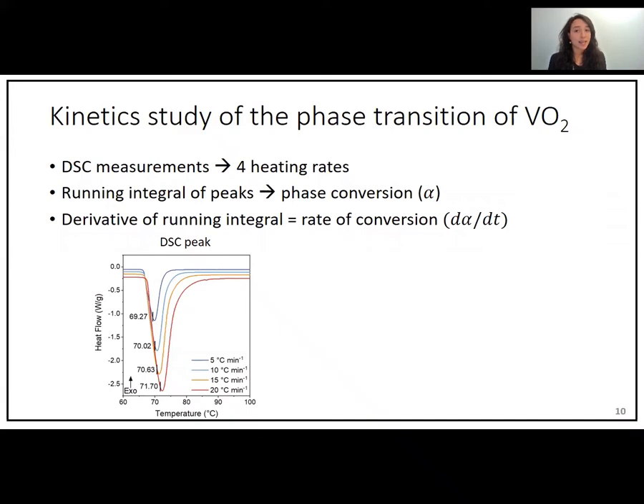Using the DSC, a kinetic study was carried out of the phase transition of undoped VO2 and doped VO2. To do this, 4 heating rates are used to look at the conversion, which is also called alpha. This is the conversion of VO2 from monoclinic to tetragonal. The image on the left illustrates the DSC measurement with the 4 heating rates.